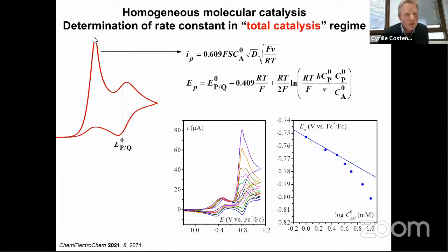But now you can get information from the position of the peak. As you can see from the expression of the peak potential, it depends on the rate constant. And as you can see from this experimental example, a different concentration of acid here, but this is not important. You can see that you have a catalytic peak here, whose potential changes with the concentration of the substrate, and from the slope here, which is 30 millivolt, you can conclude that you are in the total catalysis regime. And so from the position of the wave, knowing the standard potential of the catalyst, you can extract the rate constant.